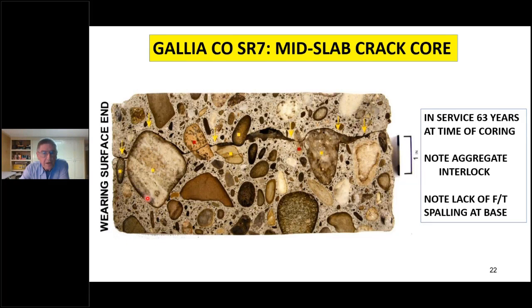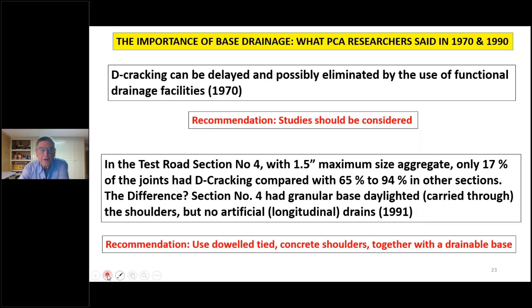This is the mid-slab crack core from the same pavement, and you see the same sort of thing here: basically a full section with the good aggregate interlock here with the 2-inch maximum size coarse aggregate. So we have a lot of things to think about here.